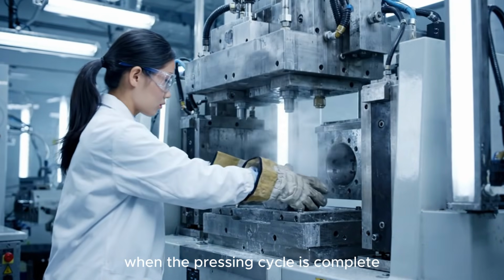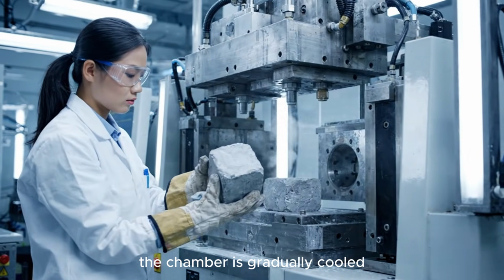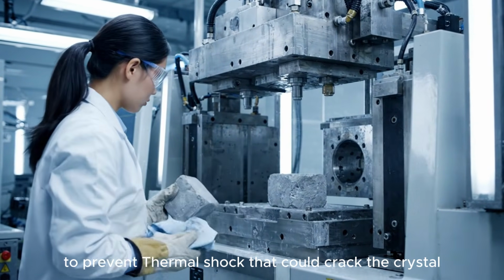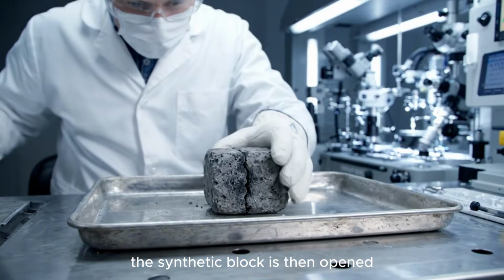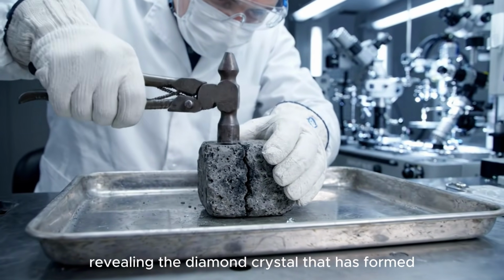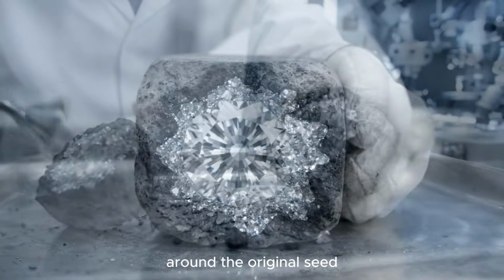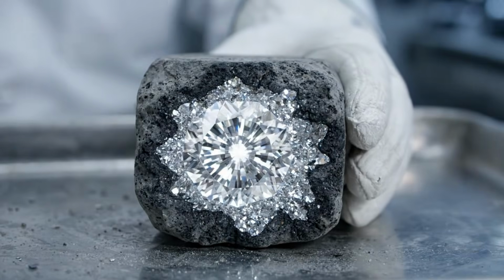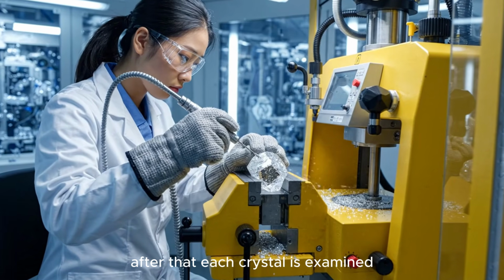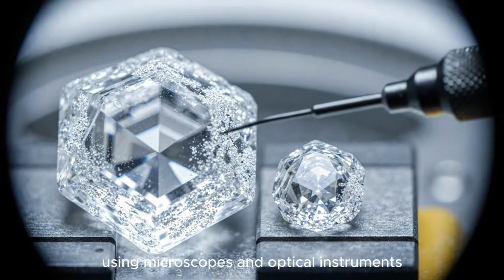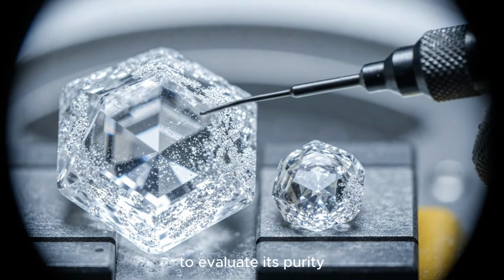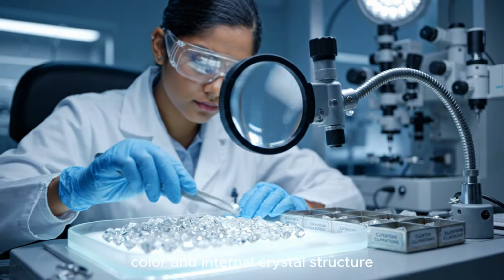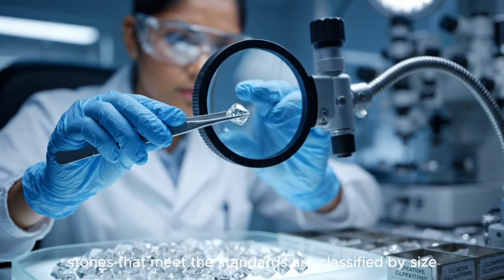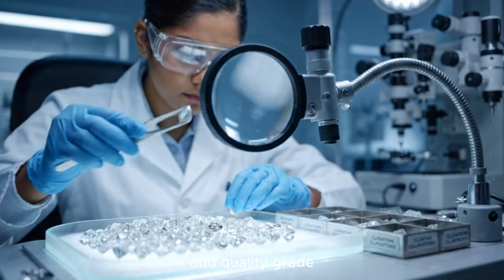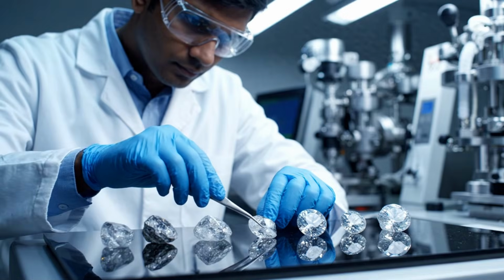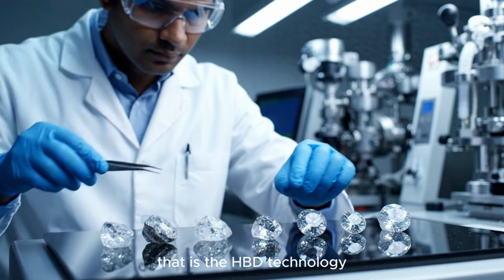When the pressing cycle is complete, the chamber is gradually cooled, and the pressure is slowly reduced to prevent thermal shock that could crack the crystal. The synthetic block is then opened, revealing the diamond crystal that has formed around the original seed. After that, each crystal is examined using microscopes and optical instruments to evaluate its purity, color, and internal crystal structure. Stones that meet the standards are classified by size and quality grade for different applications. That is the HPHT technology.